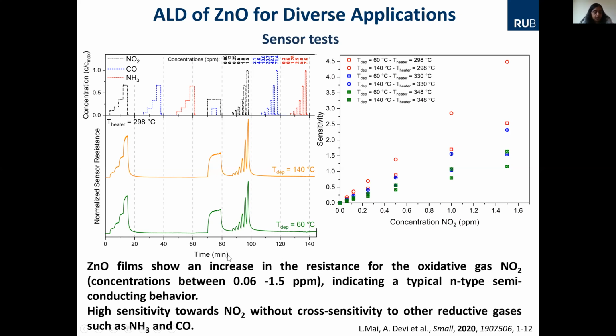We found that for the oxidative gas, especially for NO2, the concentration level was 0.06 to 1.5 ppm, and it shows the typical N-type semiconducting behavior. So there was no cross sensitivity. That is also an important aspect, because sometimes you cannot differentiate between different gases. And when we compared this to a commercially available sensor, we found that the sensor temperature was around 300 degrees centigrade. This material system actually was operating quite well, or in fact a little bit superior compared to a standard solid state sensor that is used for such applications.